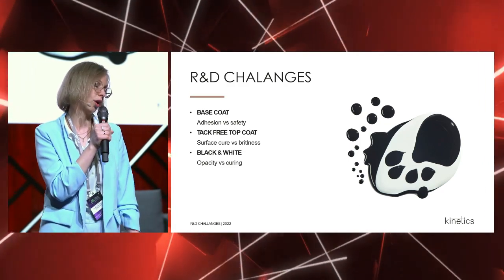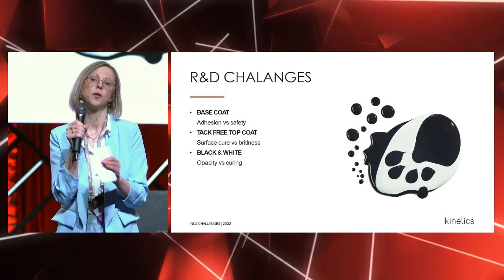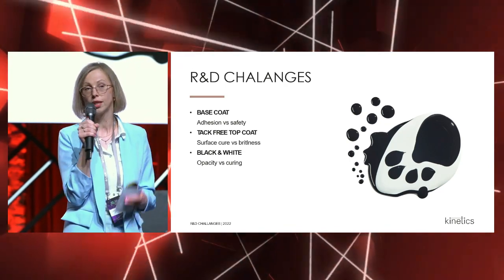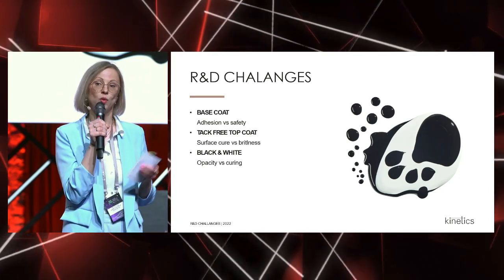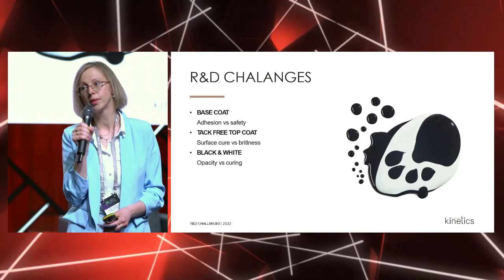And yes, one more quite big challenge is saturated pigments, because black and white pigments are really strong at absorbing UV light, but we need to get the saturated coating and at the same time polymerization in the whole coating thickness. My color team colleagues face the challenge of making pigments really saturated but still possible to polymerize in all thickness. And the quality team faces challenges regarding new methods, regarding precise color detection and color stability evaluation.